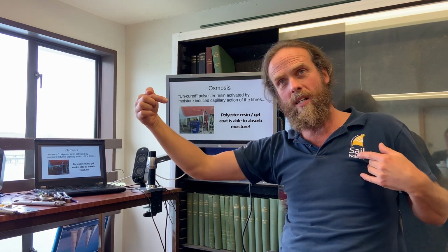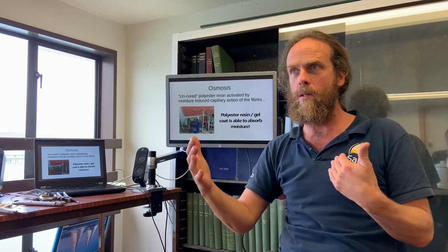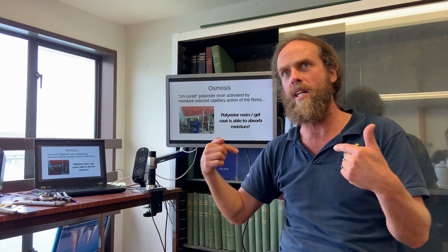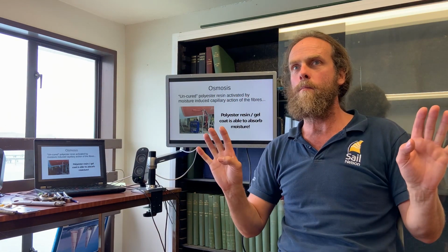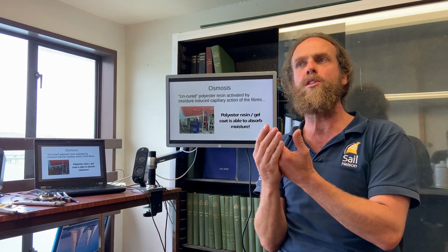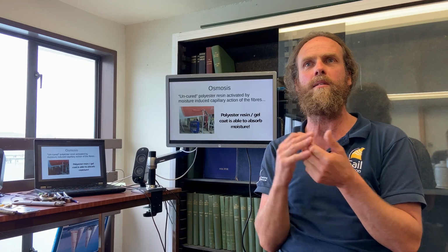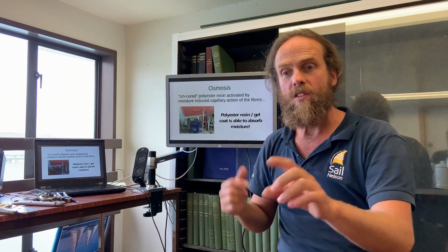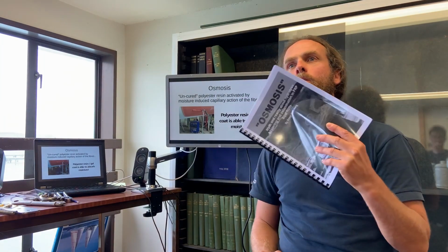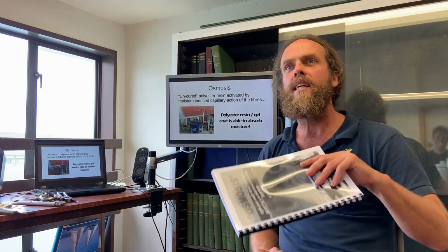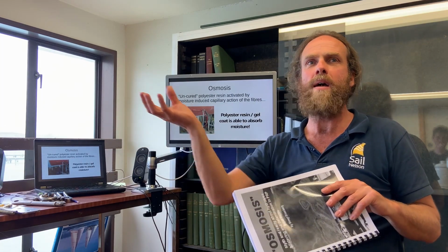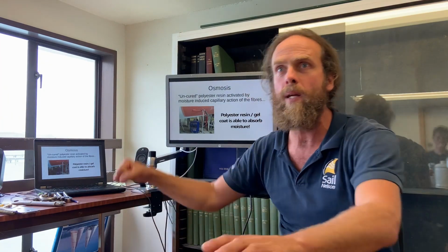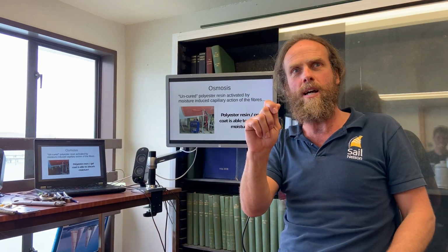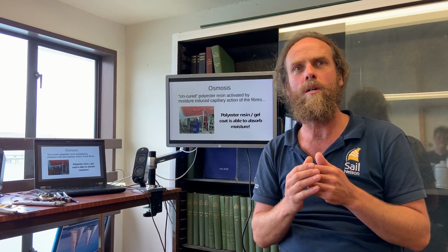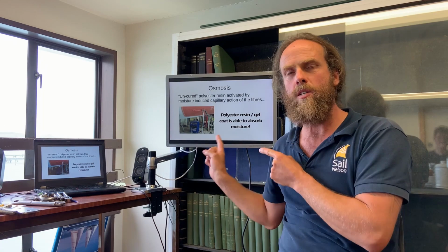They use temperature sensors on the inside skin to control the duration of the thing, with moisture sensors under there as well, and they're basically drawing out and then re-curing what's there. Not a cheap exercise. There are versions of this repair you see all around the boatyards of the world, right? Different boat builders, different ideas. Again, the reason why this guy went to the lengths he did was because he was doing all of the different repairs, and years later, 3, 4, 5 years later, the same boat's coming back with the same problem after doing these stripping, planing, putting heat lamps under, getting moisture down, but no post-cure heat soak. All right, and that's what these pads do.